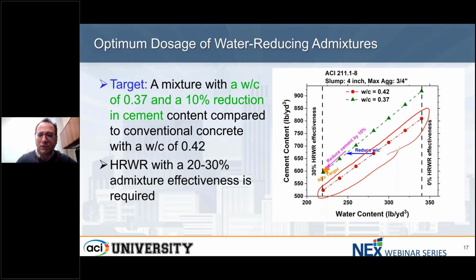And as I said, the goal is to reduce water cement ratio by 5%. So that's why I'm showing also the 0.37 graph as well, based on, again, ACI 211 requirement. So the approach taken, we are assuming we are starting with a mix design at this point with a 0.42 water cement ratio, and to give us that 4-inch slump with a certain high range water reducing admixture. The first thing we do is we first optimize this mix design. By optimization, I mean the aggregate optimization. So we're going to have two mix designs at this point. One is what we call the control mix design. The other one is the optimized control.